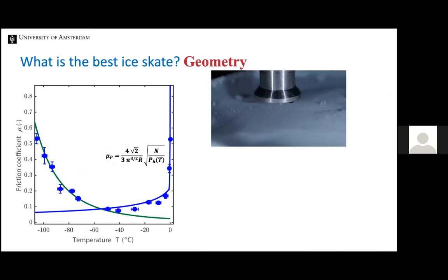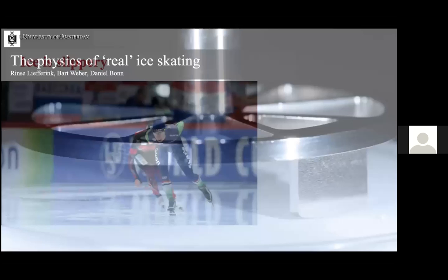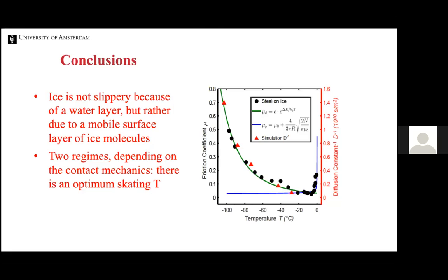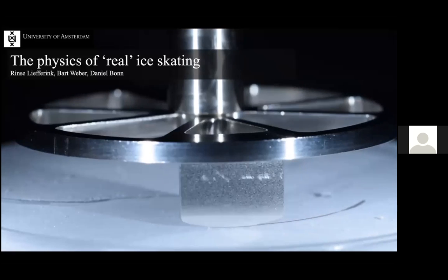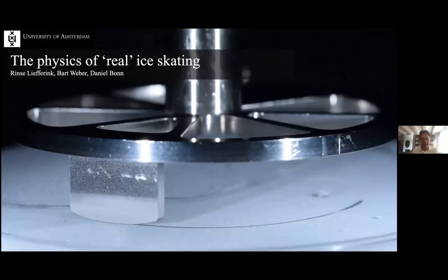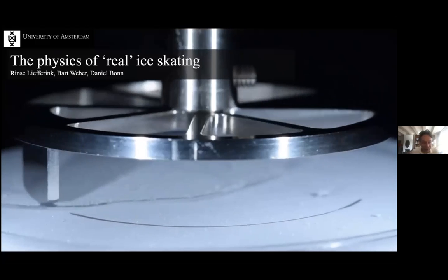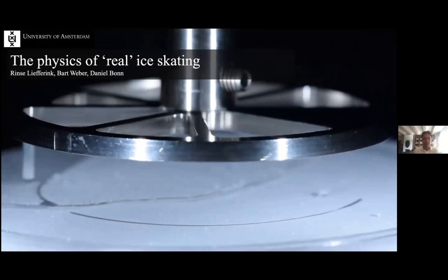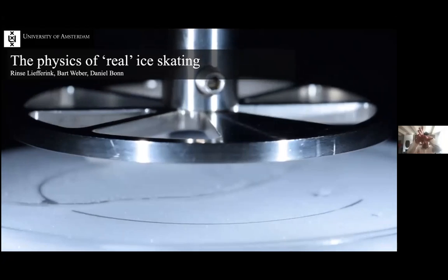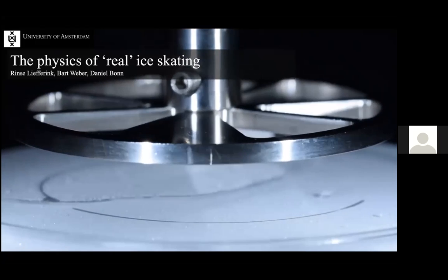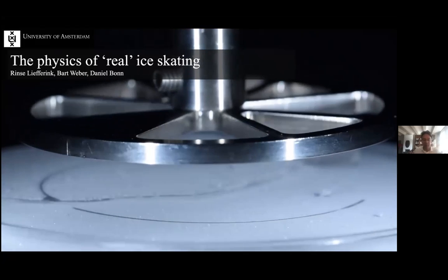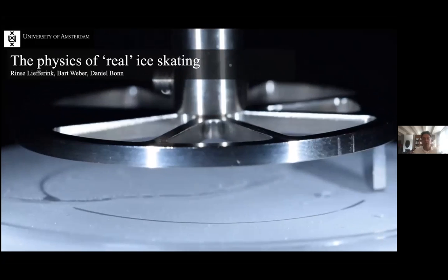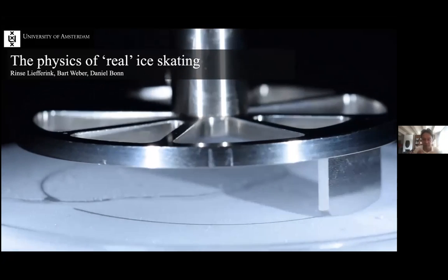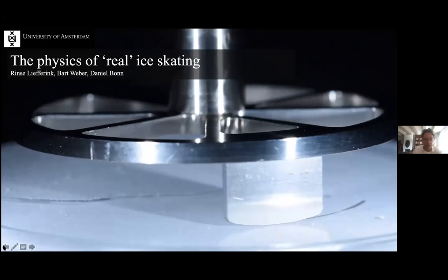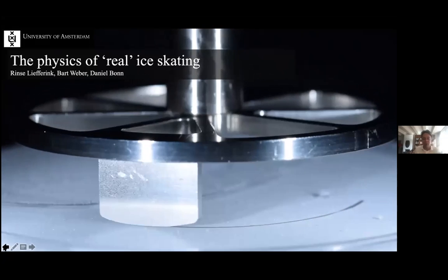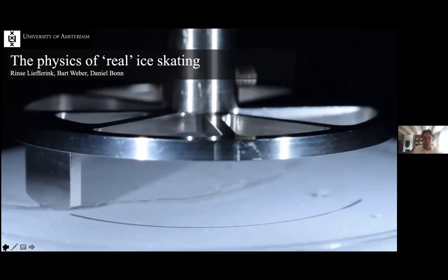So it cannot be that you must have some kind of balance between low friction and enough friction to accelerate, isn't it? Or am I wrong? Well, the friction for acceleration, if you look at this skate, comes from the sides. The sides are very sharp, and that's what allows you to have a high friction with the ice. But while you glide, you have to have a low friction. So the skate is made such. If you had a round bottom on your skate, you wouldn't be able to skate.